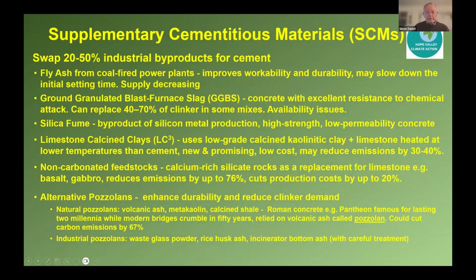Blast furnace slag. It gives an excellent resistance, but that's got availability issues. There's silica fume when you're making silicon metal. Gives you a high-strength, low-permeability concrete. You can use low-grade calcined kaolinitic clays to go with the limestone, and you can lower the temperature. So these are all ways that we can lower the emissions. And then also there are feedstocks like basalt, which haven't any carbonate in them. So that will reduce the emissions.